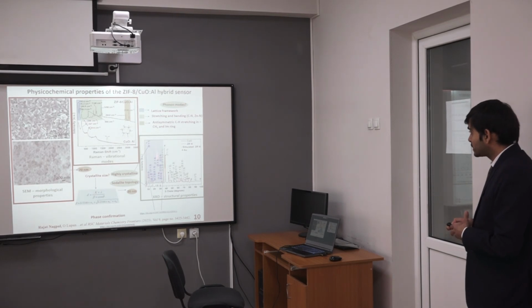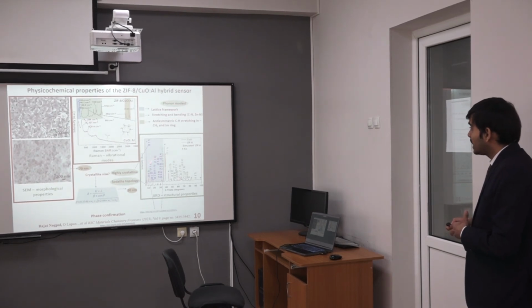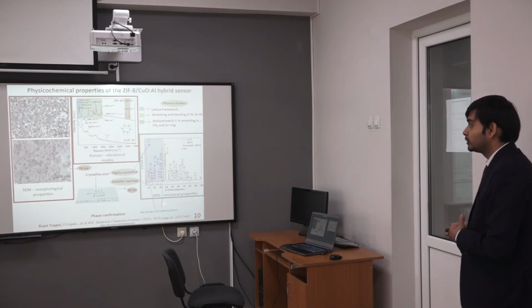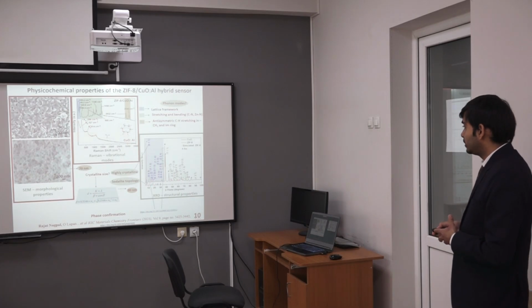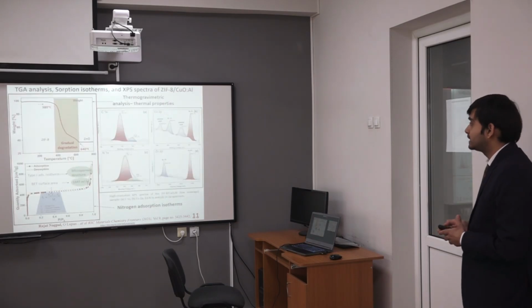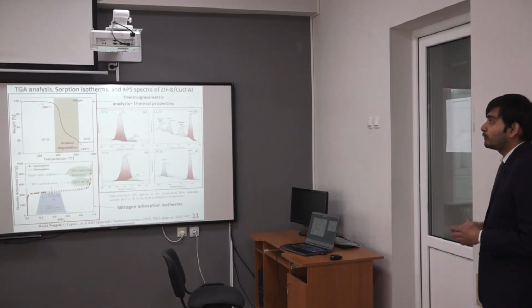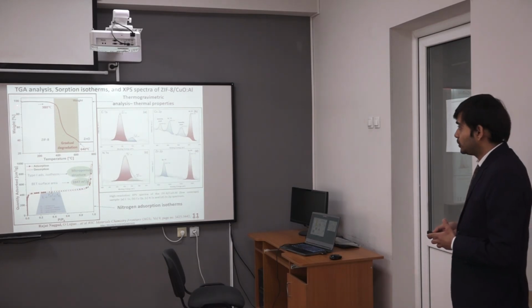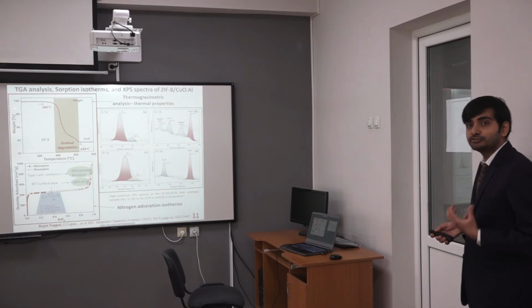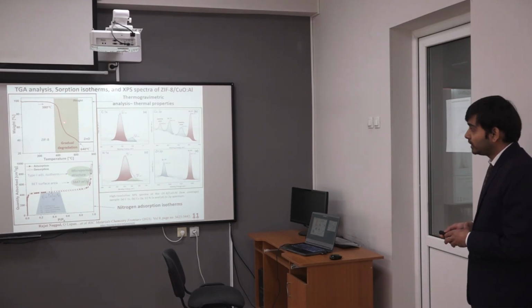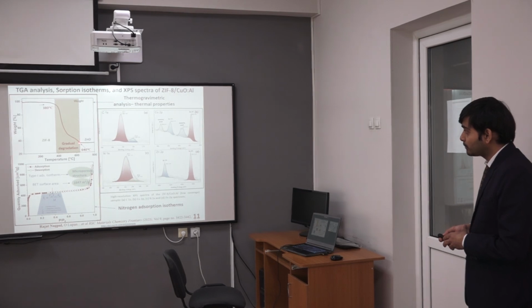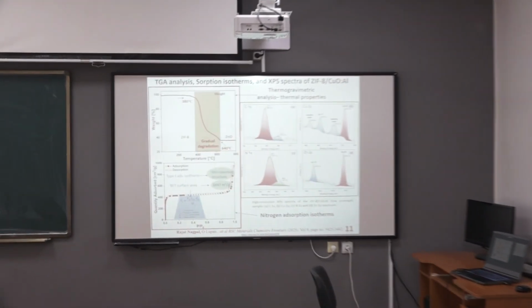Here we can see specifically this blue region, which gives highly crystalline XRD peaks for ZIF8, and comparing it with other reported literature, it shows sodalite topology. And using the crystallite size Scherrer equation, we can calculate the crystallite size. Now, to get insights about the thermal stability, here we can see TG analysis going from room temperature up to 380 degrees Celsius. It retains its structural framework, and then gradually it degrades with increasing temperature and transforms into metal oxide.